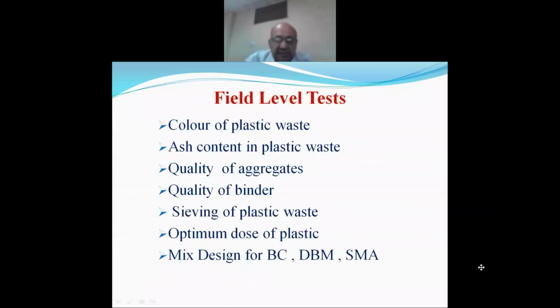Now I am coming to the requirement of the quality control. Aggregate, bitumen and filler shall be tested as per requirement of subsection 504 for BM, 508 for BC, MSS, and 510 for open graded premix carpet. Plastic waste shall not be black, and shall meet the requirement of IRC specification. It may contain LDPE, HDPE, etc.